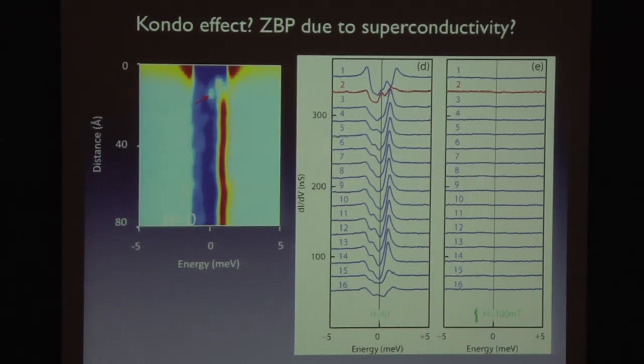Once you have no superconductivity, you have no features in the data whatsoever. This just looks like basically a piece of magnet. We can do measurements to show that it is a piece of magnet with nothing very exciting going on in it. So you need superconductivity to create these particles that are showing up as in-gap states and those 0 energy states.